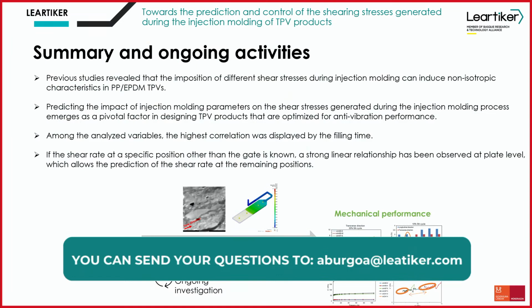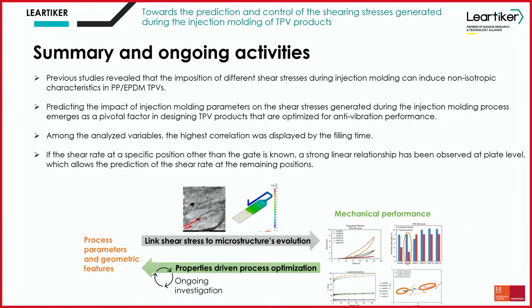And in the case of the project, we saw that among the analyzed variables, the highest correlation was with the filling time. And it was interesting to observe that if the shear rate at a specific position other than the gate is known, a strong linear correlation exists with the other positions at plate level, which allows the prediction of the shear rate at the remaining positions. So we can have a full overview of the effect of the processing on the shear rate in different locations of the plate. And as an ongoing activity, during this project, we have been linking how the process parameters affect the shear stress and the microstructure evolution.